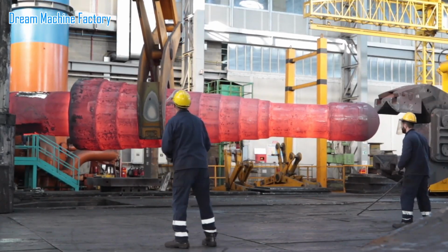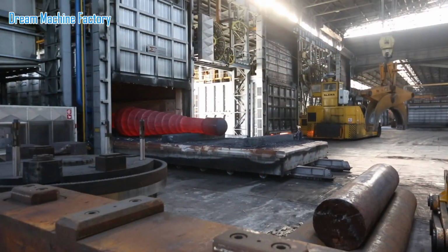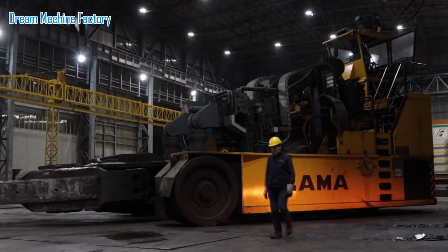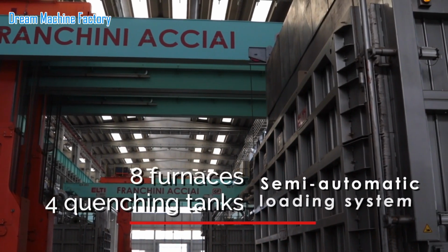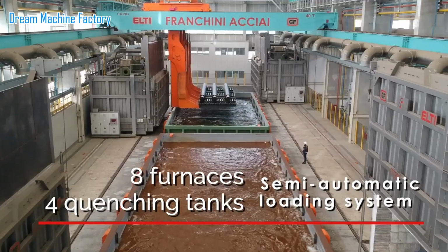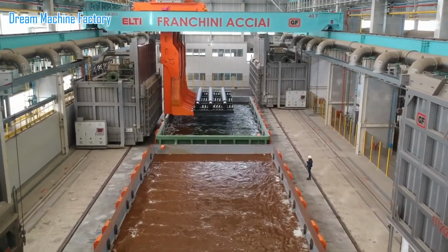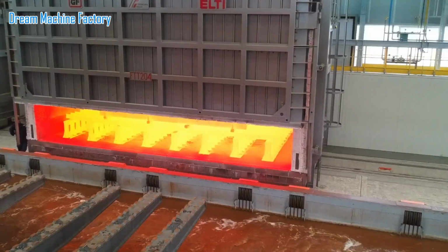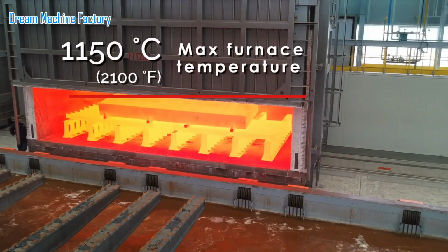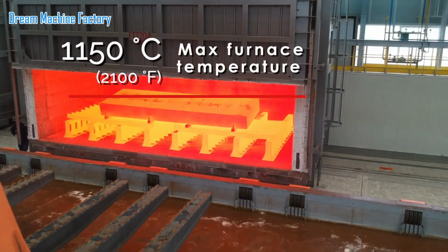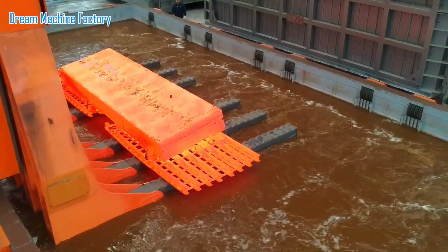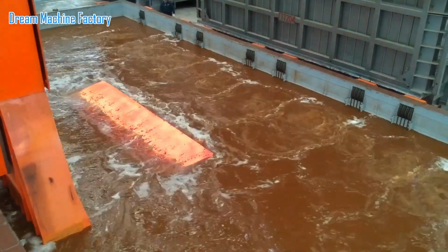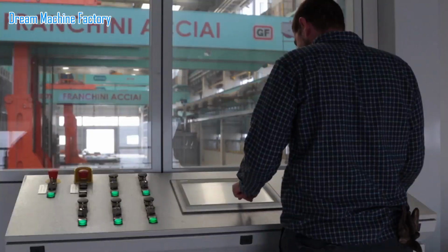Franchini Acciai's heat treatment facility features 8 advanced furnaces capable of reaching temperatures up to 1,150 degrees Celsius, 2,100 degrees Fahrenheit, ensuring optimal thermal processing of large forged parts. 4 quenching tanks, using water or polymer, are supported by a semi-automatic loading system, enabling efficient, controlled, and uniform heat treatment for enhanced material properties.